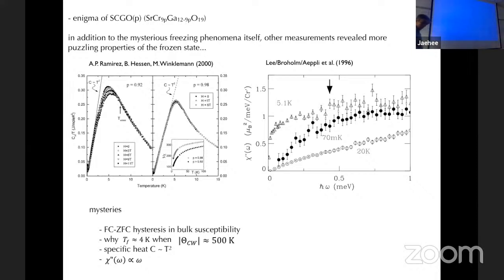But I think this is a glassy state. So in fact, this is consistent with the quadratic specific heat and the linear dependence of chi double prime of omega. They are consistent because the density of states goes as omega to the d minus 1. So it is two-dimensional, so that explains it, and then specific heat goes as T to the dimensionality.